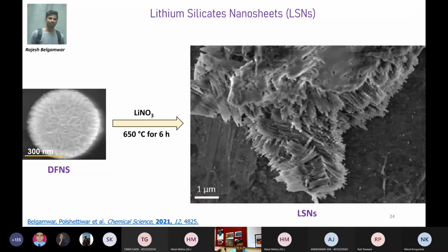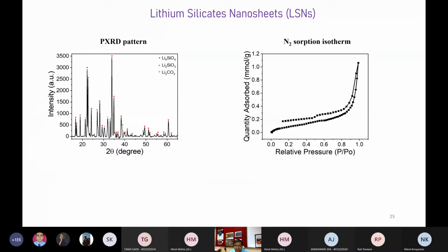So the idea was to convert the DFNS into lithium silicate with a morphology like DFNS. That was the hypothesis. Obviously, that doesn't work. DFNS breaks down in presence of lithium nitrate at 650 degrees Celsius. It is stable otherwise up to 800 degrees Celsius, but in presence of lithium nitrate, no. And we were never able to make lithium silicate like DFNS. But what we got is some sort of a degraded DFNS sphere with sheets, and these lithium silicate nanosheets fortunately also work efficiently to capture the CO2.